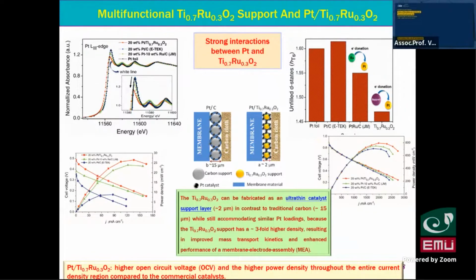But for our catalyst, we need just a little catalyst, so we can make an ultra-thin catalyst support layer with the same amount of catalyst compared to traditional carbon. That means when we make this very ultra-thin catalyst support layer, we can enhance the mass transport kinetics, which enhances the performance of the membrane electrode assembly, MEA, for the fuel cell system.